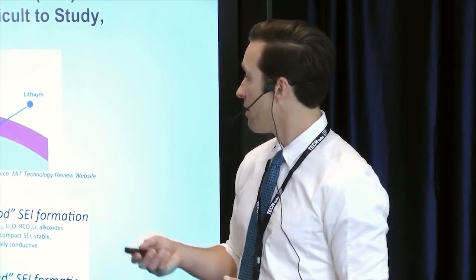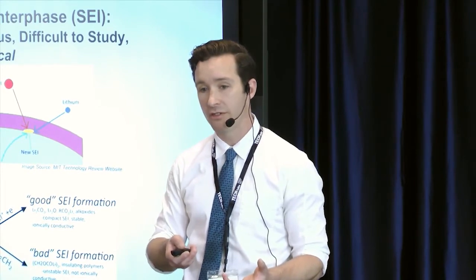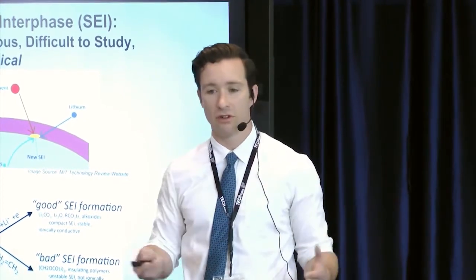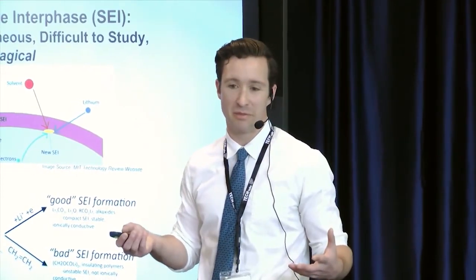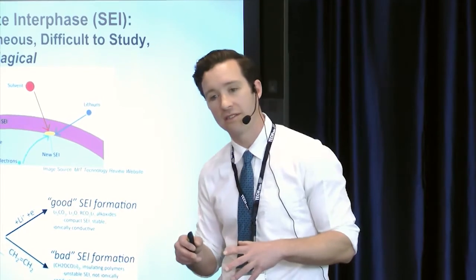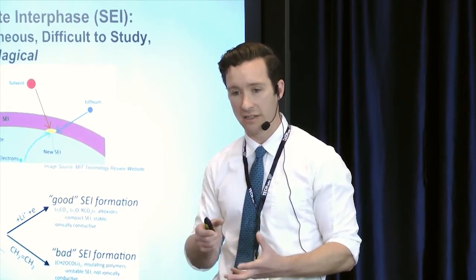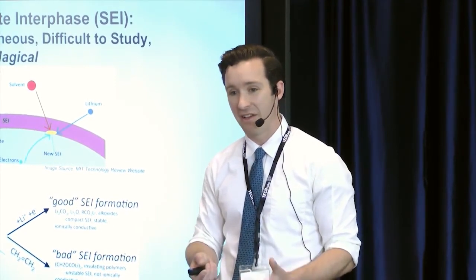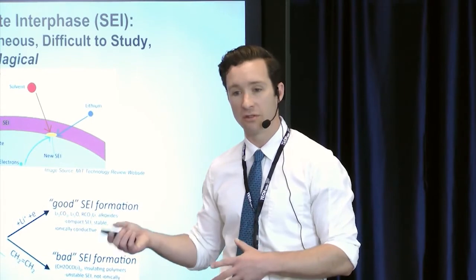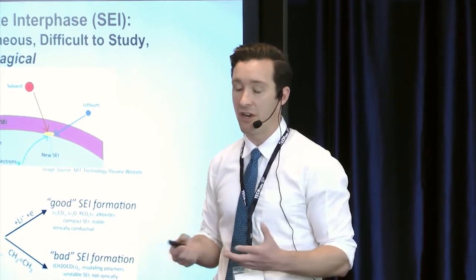But a lot of the other ones are going to be better for long-term energy storage. You can do grid storage applications, because if you have a giant truck in the middle of the desert with your batteries, who cares if it's a little bit bigger than it needs to be? The bulk coating processes, where you've got the graphene-encapsulated silicon, you can coat much thicker and get higher energy density, but the rate capability is not great. So for low power devices or long-term storage, those are going to be better because you can operate them at a slightly higher voltage. You can slow down this decomposition, but you're not going to get very good rate.